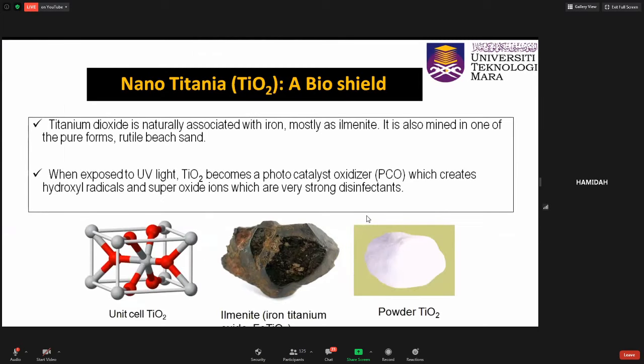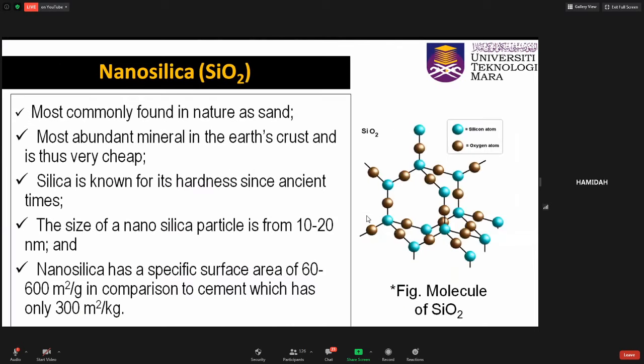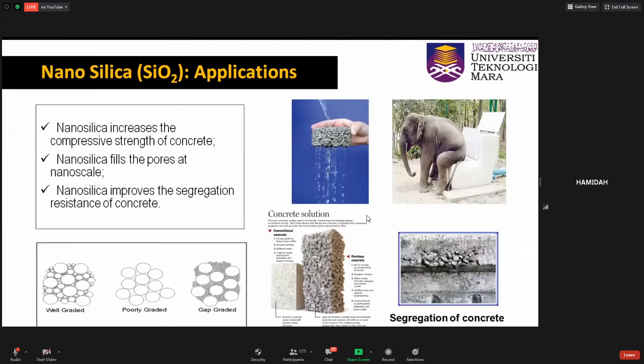Nanosilica, because of its cheaper cost, is the most commonly used. Silica is found in nature as sand. Nanosilica particles range from 10 to 20 nanometers. Nanosilica, when incorporated in concrete, would fill the pores at a nanoscale, resulting in increase in compressive strength of the concrete and improved resistance towards segregation.